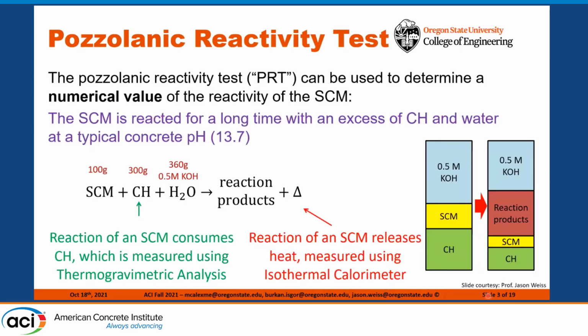The pozzolanic reactivity test is designed to determine a numerical value of reactivity for supplementary cementitious materials, or SCMs. The SCM is reacted with an excess of calcium hydroxide and a 0.5 molar potassium hydroxide solution for 10 days. The consumption of CH is measured by finding the remaining CH using thermogravimetric analysis, and the heat release is measured using isothermal calorimetry, and then a degree of reactivity, or DOR star, is calculated.